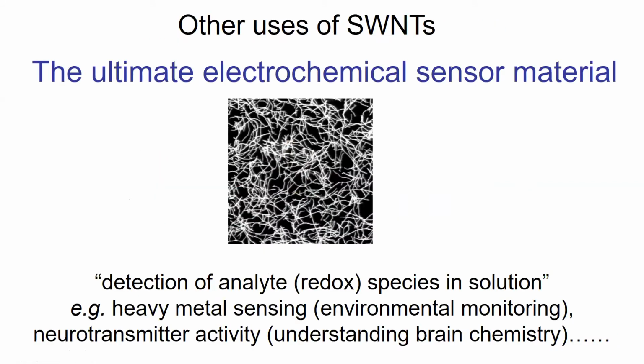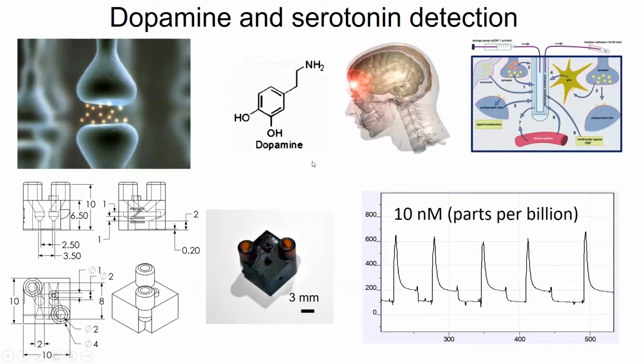Other things I do is I look at using them as sensors. I sense species, either in solution or predominantly in solution, but sometimes in the gas phase. And I use these mats here of nano electrodes, these nanotubes, to do this sensing. Just one application is we work with colleagues down at Imperial College London, and we're interested in sensing these neurotransmitters, dopamine and serotonin. So these are important signaling molecules, and they can be oxidized or reduced. And we can detect the oxidation or reduction of these species by measuring a current at our nanotubes.